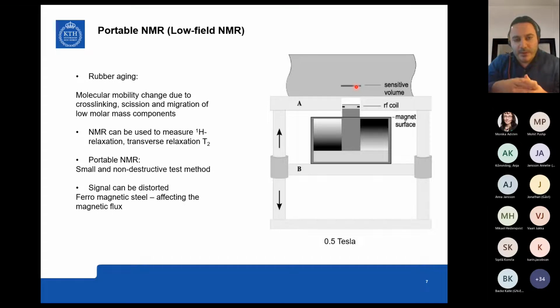So essentially, as you age your material, as you're cross-linking it and it becomes more and more stiff, it's going to affect your T2. So you're going to get a shorter T2 as you age your material. It goes really well hand in hand with aging, I would say, the transverse relaxation times, and it gives you a good indication of if your material is actually aging.